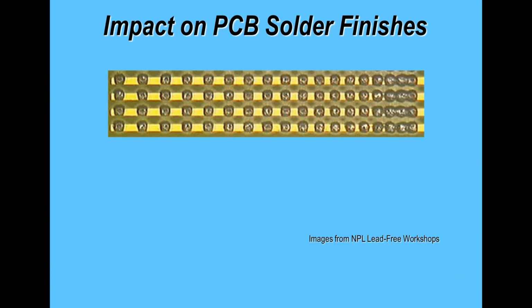Now, one of the little tricks that I use all the time, and it's quite useful, and I suggest this for looking at your performance, solderability or wettability in your reflow process, be it convection reflow in air, nitrogen or vapor phase, is wetting indicators. And I've used these, as I said, for quite a number of years. And if you're interested in monitoring the wettability or solderability of your surface finish and possibly the interaction with nitrogen, then this is something very, very simple at no cost to introduce over a period of time.